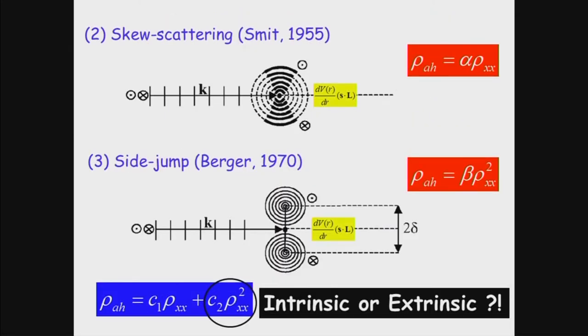But fifteen years later, Smit and Berger argued that this anomalous Hall effect must be an extrinsic effect. It must be coming from the impurity. Smit argued that with this skew scattering mechanism, it should be a linear relation. But Berger argued that besides the skew scattering, one should also expect a quadratic term, the side jump. So since then, in the literature, people have had these two terms. This one is called skew scattering, and for this one it is not clear whether it's intrinsic or extrinsic. It's so controversial, and I should give you the flavor of how controversial.